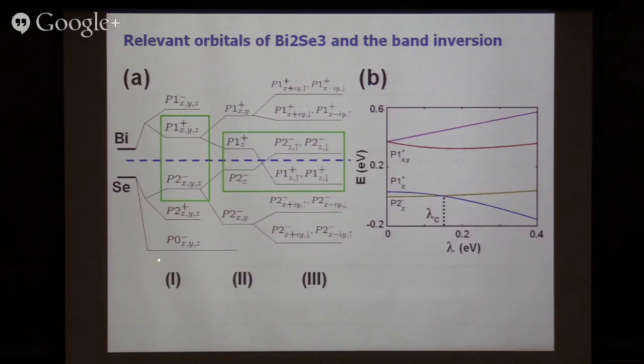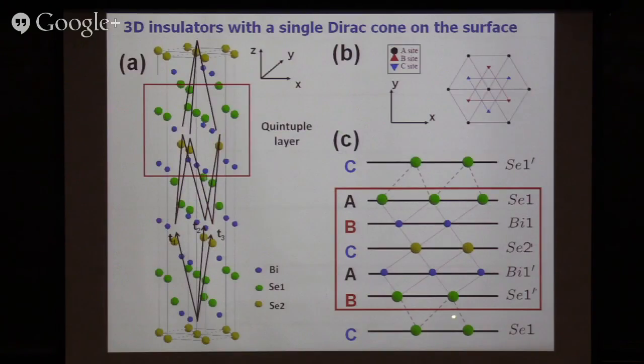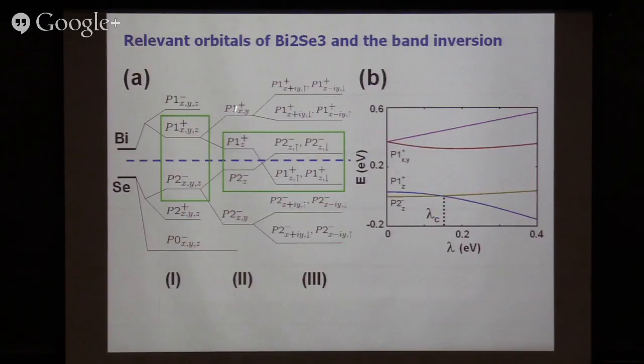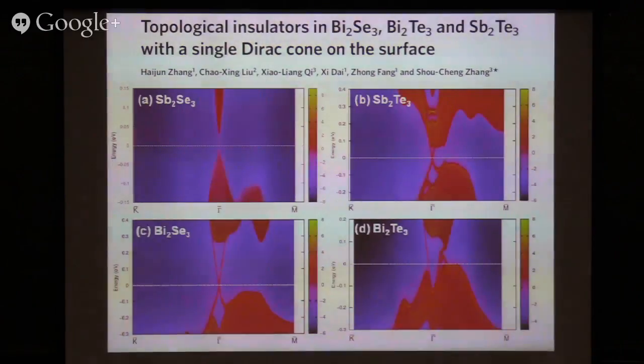But in this case, they're mostly p orbitals in the system. In the case of mercury telluride, we have an sp level inversion. But in this case, because of the layered structure, you can form bonding and anti-bonding p orbitals. And by spin orbit coupling, the bonding and anti-bonding p orbitals lead to a band inversion, which is the key to topological insulator behavior. Nature gave us four different materials, and they have different strengths of spin orbit coupling. Our theory calculation shows that antimony selenide doesn't have enough spin orbit coupling, but all these three have enough spin orbit coupling, so that a band inversion happens.